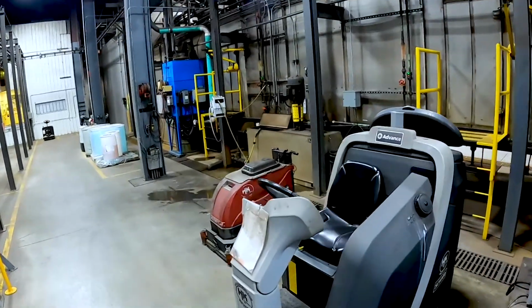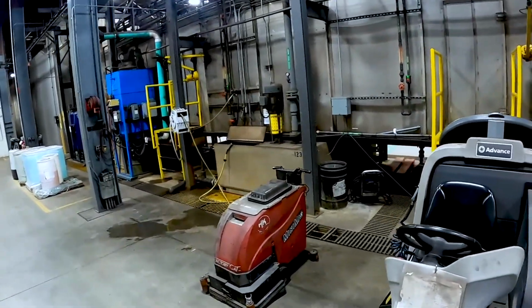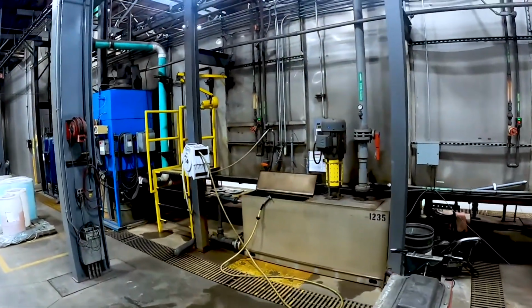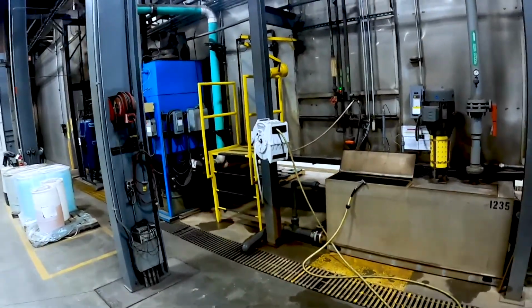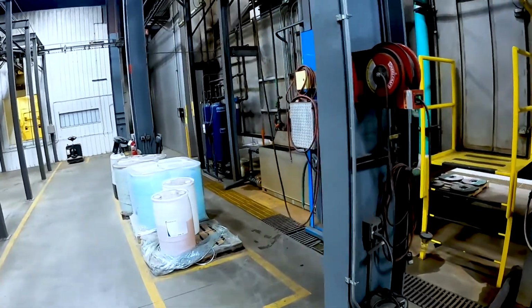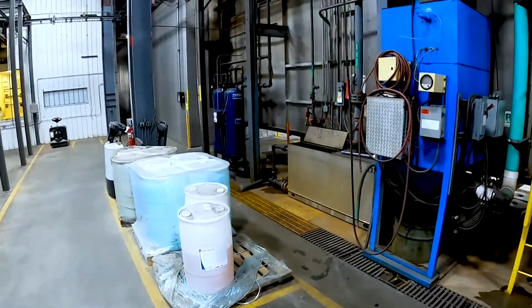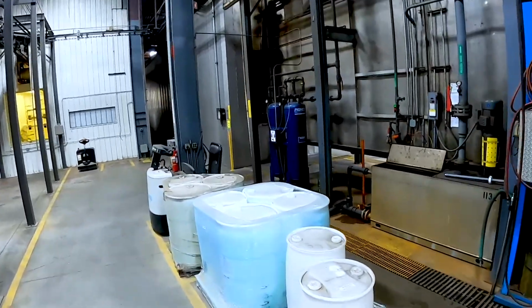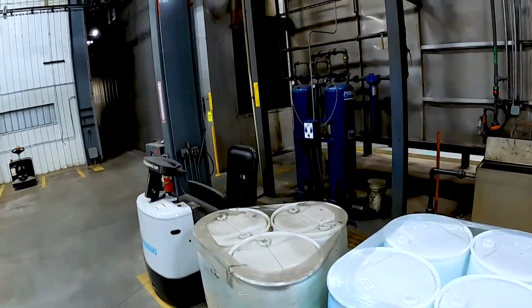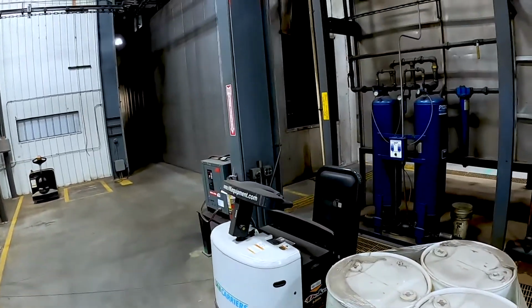Stage 4 is a rinse that rinses down to make sure the zirconium is not too thick. If it's too thick, the paint won't stick to it, or it will outgas up through the paint, ruining the finish. The 5th stage is a final rinse, just to make sure everything has been rinsed clean, the zirconium is not too thick, and to keep the part moist for when it goes through the dry off to keep it from flash rusting.